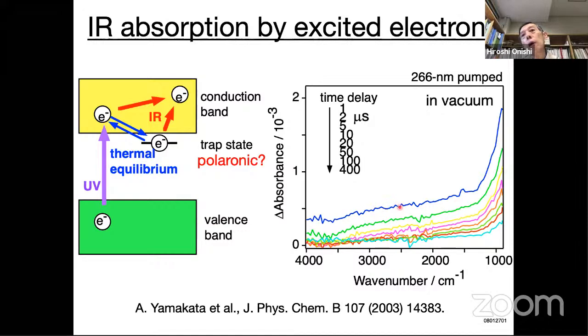So positive absorbance change means that by irradiating ultraviolet light, infrared absorption intensified. These colored line spectra show the experimental results. When we irradiate the photocatalyst, say, look at the blue one here, this blue spectrum appeared. This means this form of infrared absorption appeared, induced by ultraviolet light irradiation. And this spectrum can be assigned to electron absorption. So this electron absorbs IR light in this way, then presents this form of absorption spectrum. Then we can know how many electrons are in the conduction band by monitoring the absorption intensity.